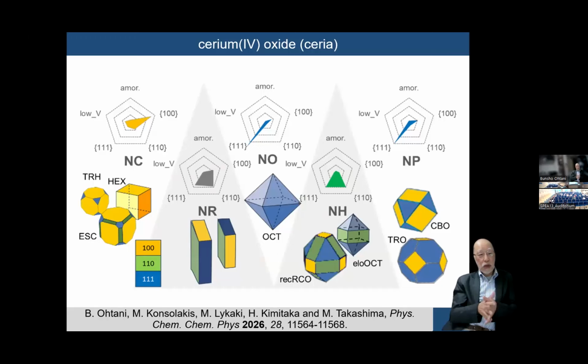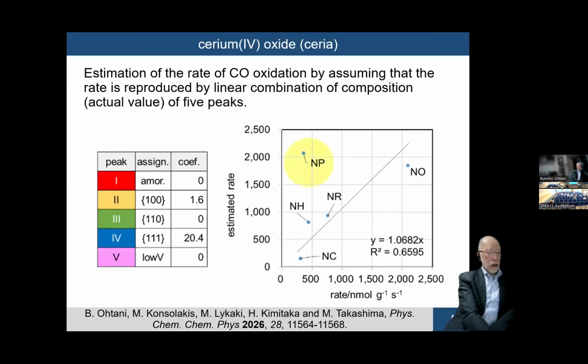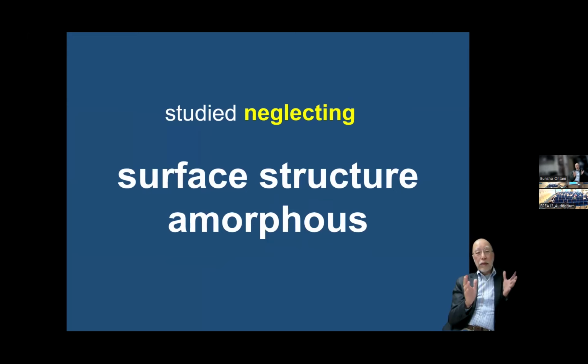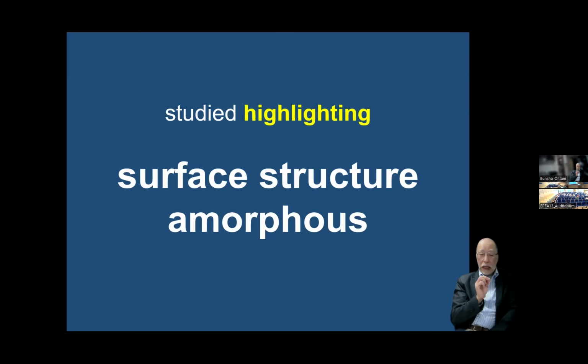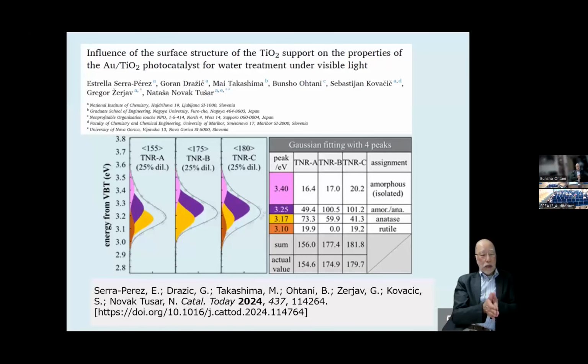That is the first example of showing the quantitative measure, the proportion of exposed surface facets. And by checking this radar chart, it is possible to see the actual morphology. Okay, so previously, the surface structure and the amorphous phase were neglected in the discussion of photocatalytic activity. However, by highlighting the surface structure of amorphous obtained by ERDT-CBV pattern, we think it is possible to discuss more deeply.